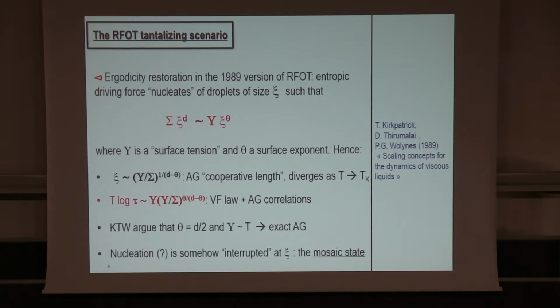Okay, but so in finite dimension, one expects these barriers to be crossed, and then comes this paper that Francesco told you about already, which is probably at that moment that myself I got aware of all this. And what is argued in that paper is that ergodicity restoration, the crossing of the barrier, arises from a kind of nucleation argument, like transitions that exist in mean field that are destroyed by nucleation in finite dimension. And so the argument of this paper is to say that there's an entropic driving force coming from